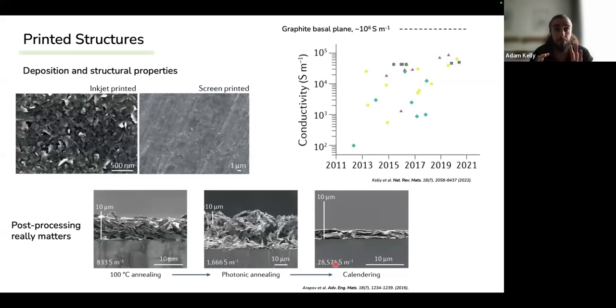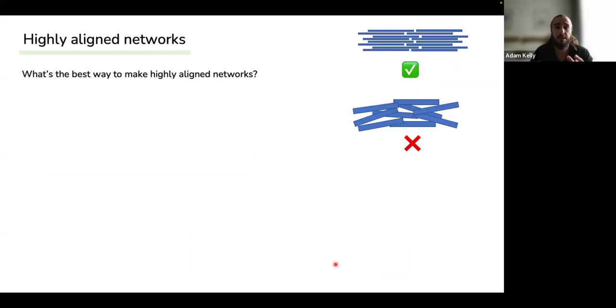So the post-processing is really what counts here. What do you do with the network after you've printed it? So the alignment, the compression there, as we saw, is very, very important. What we want for high performance of conductivity, for example, or mobility, is a network with nanosheets that look like this, and not a network with nanosheets that look like this. So what's the best way to make these highly aligned networks?